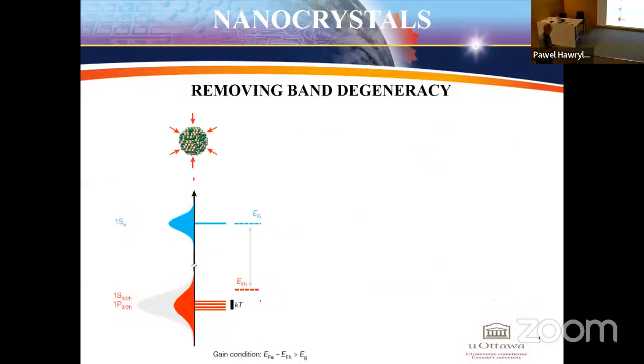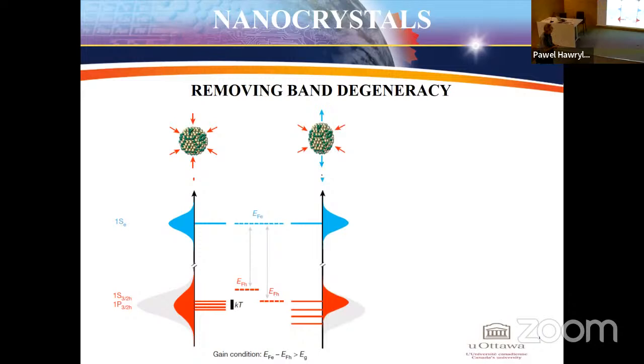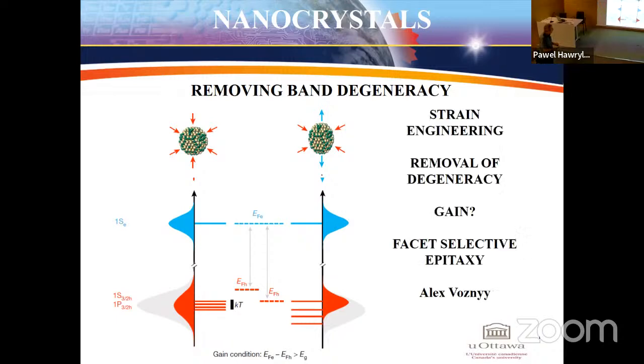So then one more time, this is our situation, and it is not changing if we have biaxial strain. Anyway, we strain it uniformly. But if we strain it, pull it in one direction, then we split this degenerate shell into well-defined levels, and this brings the Fermi level in the valence band into this level, so there is a hope to achieve gain. Yes, so strain engineering, removal of degeneracy, demonstration of gain, and this is achieved through facet-selective epitaxy, driven by my colleague, slightly younger, Alex Voznyy.